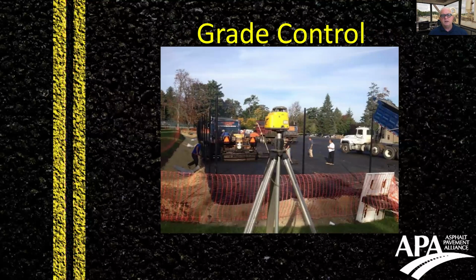Grade control is the big thing with these types of projects, and this is something, even though my practice has been mainly limited, at least over the last few decades, to the NCAT pavement test track, grade control is a really important thing to us, because when we are doing research thickness, we need to build pavements to precise thickness, and then we need to have smoothness that's very, very good, so that roughness doesn't confound the outcomes of our experiment. So I'm very sensitive to the grade control issues, but sport courts are a whole new thing, and it's because of that 1/8 of an inch tolerance over 10 feet with a straight edge. You have to make sure that you have this under control.